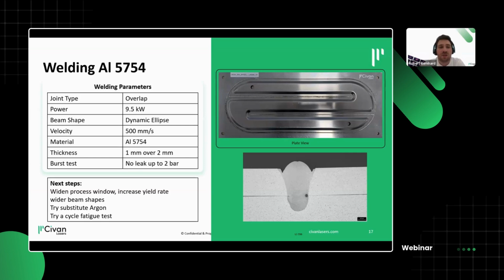And finally, one thing we are currently working on is to substitute the argon. So these processes have been done with argon shield gas in order to reduce oxidation. But getting rid of argon, which is just a consumable, is one of the next steps, while even increasing the yield rate, the process window, maybe making it even wider or working on the surface finish. But for us, this is definitely a breakthrough in achieving 500 millimeters per second, 30 meters per minute, consistent welding speed, leak tight on these aluminum plates.